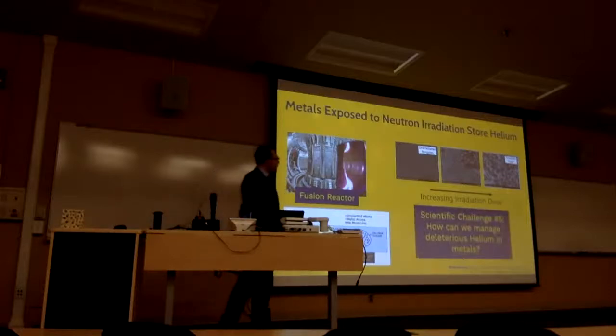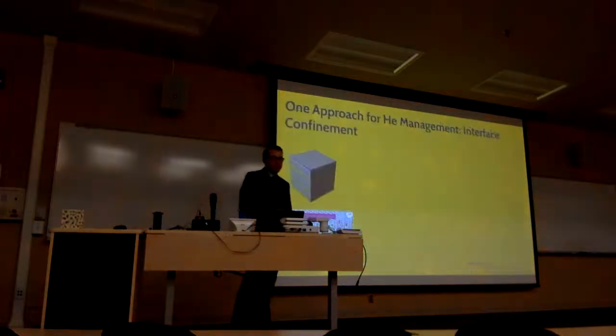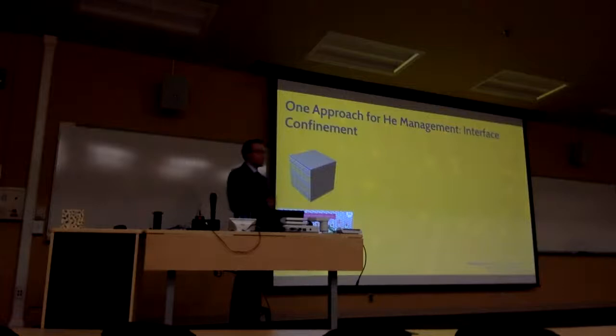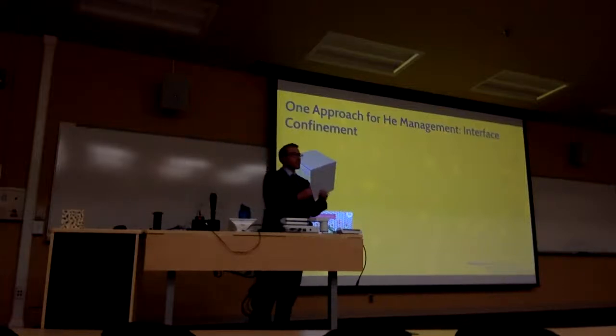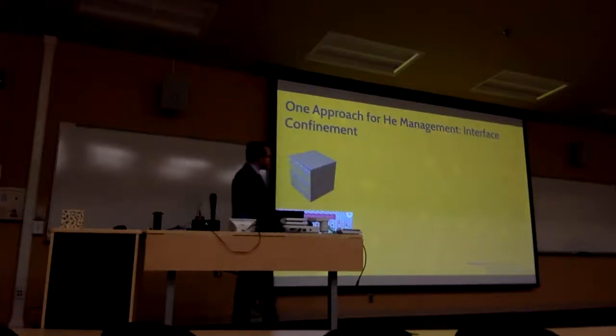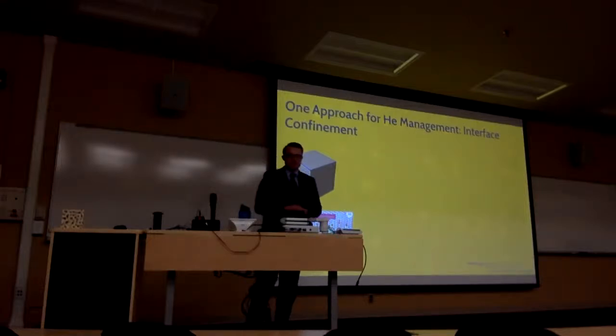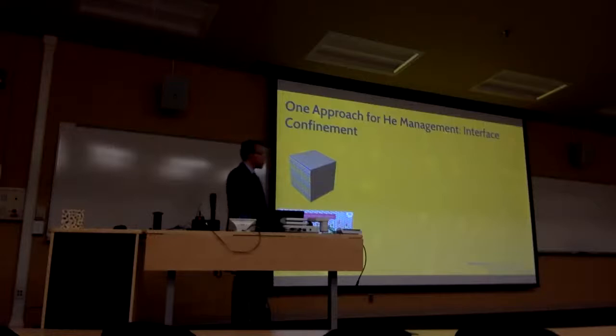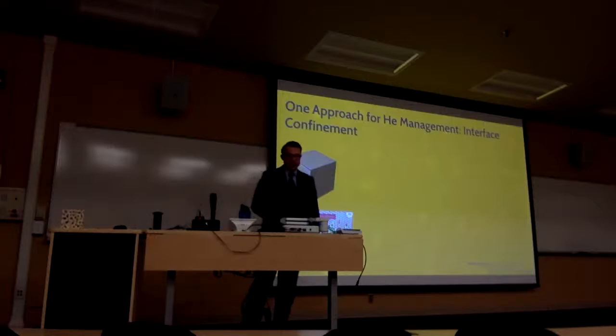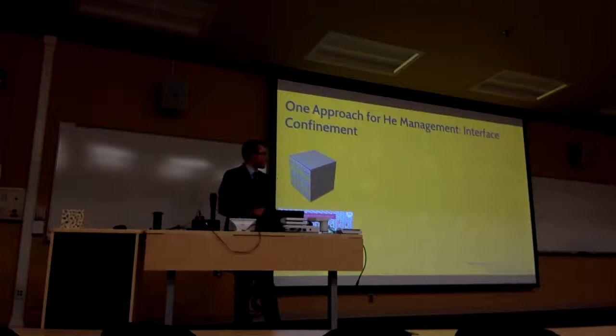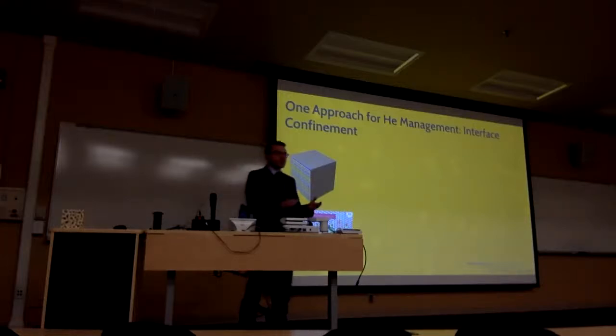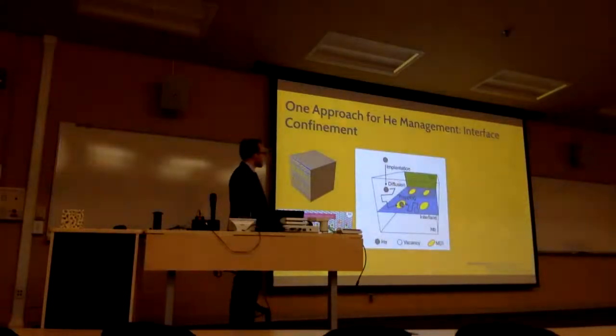So the scientific challenge here is, how can we manage the deleterious helium that gets trapped inside the material? You could possibly think of two approaches to solve this problem. One approach might be to confine helium in very specific locations inside the sample. This multi-layer design, like I described before: if we interface a BCC and FCC material, we create misfit dislocations across the interface. And these are very useful in terms of helium entrapment, as helium atoms like to diffuse to that location at the interface.